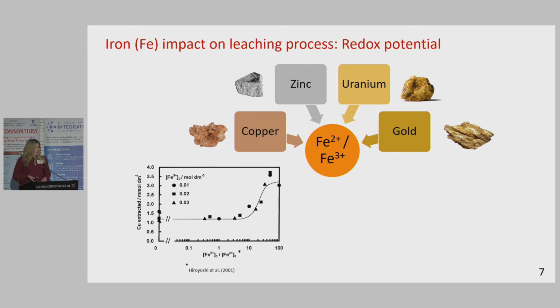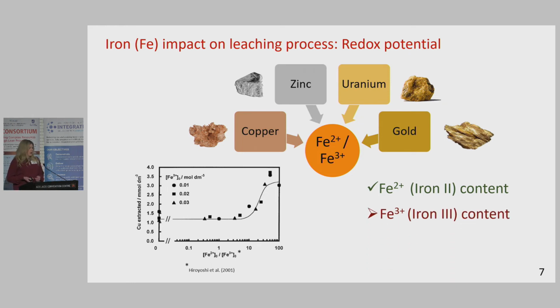For example, a study done in 2001 showed that optimizing the iron 2 to iron 3 ratio in the copper leaching process allowed the authors to increase the copper recovery up to 3 times. We have good, reliable methods for measuring iron 2 concentration in solutions. However, iron 3 concentration is a lot more difficult to measure. It requires extensive sample pretreatment. It needs expensive, complicated equipment. It's a long process, and a lot of times the measurement we obtain is not exact and precise because we're not determining the iron concentration directly.